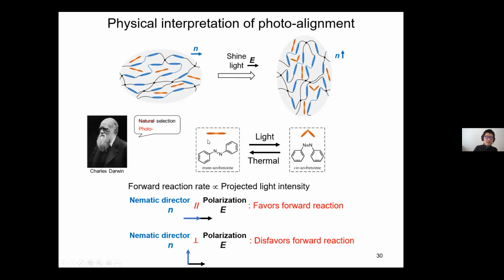So imagine now in the equilibrium state. You have a forward light reaction and you have backward thermal relaxation, and you just move in equilibrium. It just goes forward and backward, cycle by cycle, right? Now, the forward reaction rate, at least in this model, is assumed to be proportional to the projected light intensity on the nematic director. If they're aligned with each other, the forward reaction is favored, it's the largest. But when they're perpendicular, the forward reaction is the weakest. So imagine you have forward and backward. It's like this molecule dies and then revives, dies and revives. In the end, if it wants to survive, just like a virus, it must stay in the perpendicular direction so it doesn't die that easily. So this is the explanation from my side.